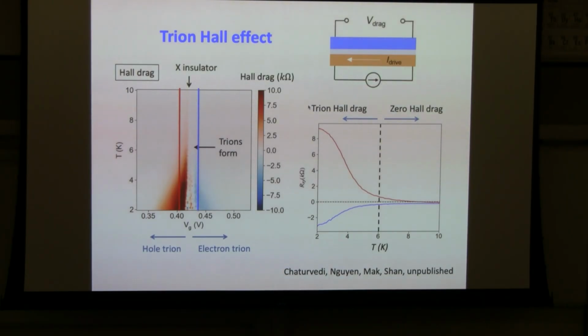So another experiment, this is the final slide, just bear with me: you can drive a current in the electron layer and measure the Hall voltage in the drag layer. Maybe this is even cleaner because you see a drag that must be coming from the bound states between the two layers. So again, this is the Hall drag as a function of temperature and the electron-hole density imbalance. These are the two line cuts. You can see that you pretty much have zero Hall drag at high temperature because there's almost no drag. But once you form the trion, on one side you get a Hall drag resistance, and on the other side you get the electron drag resistance. Okay, so I think this can only be explained by the formation of the trions.